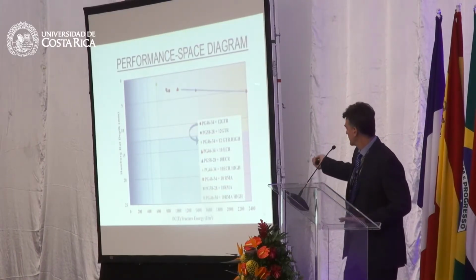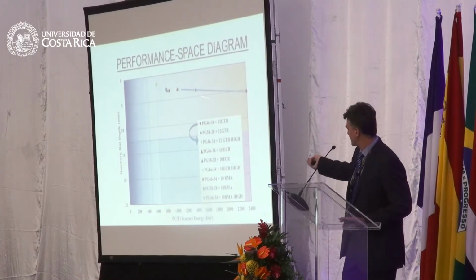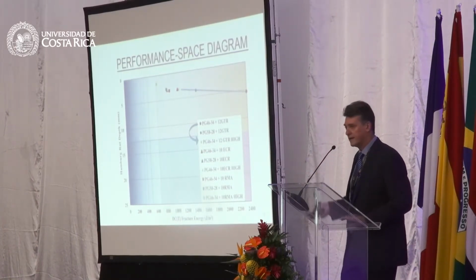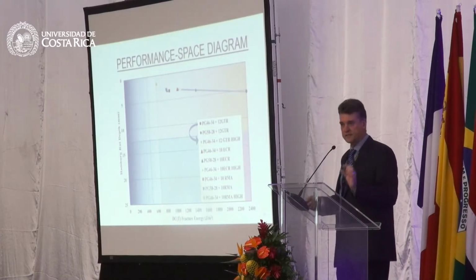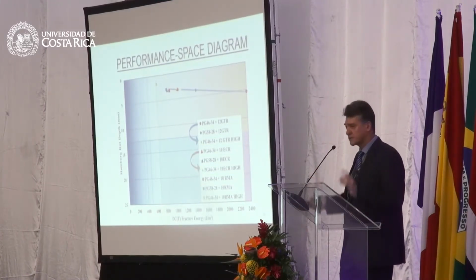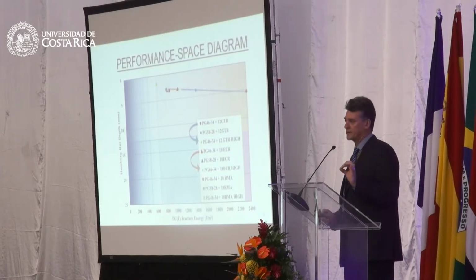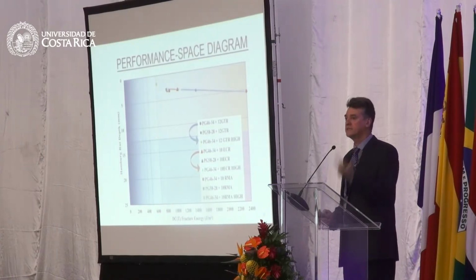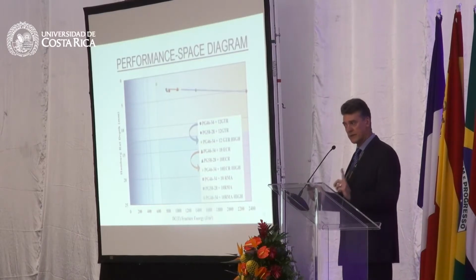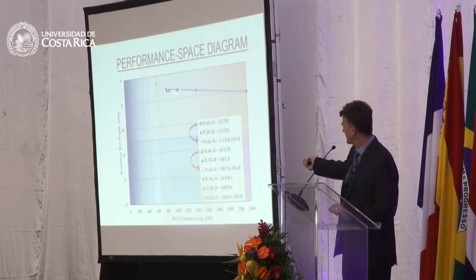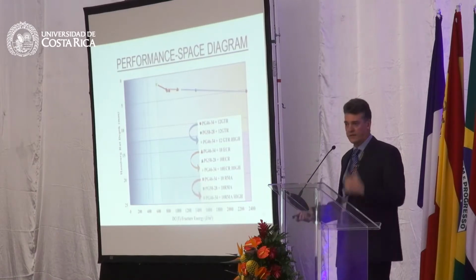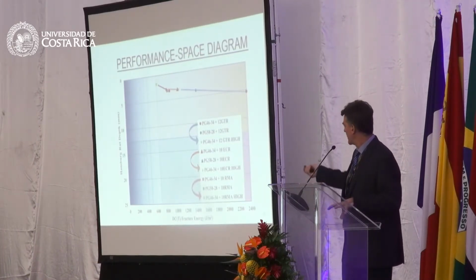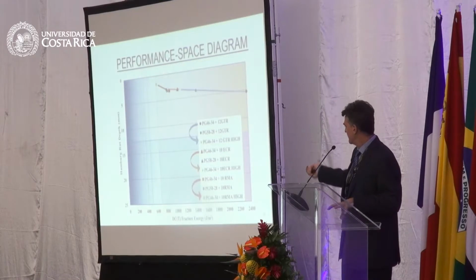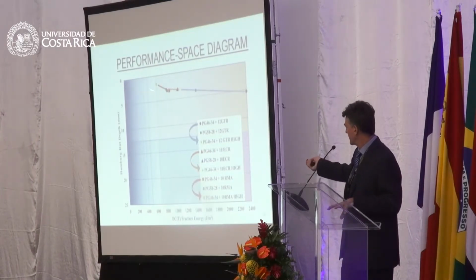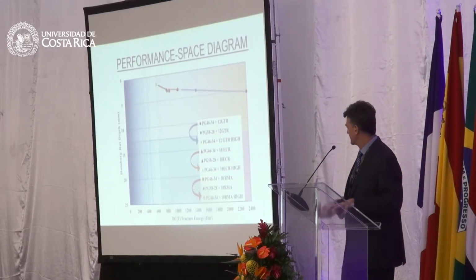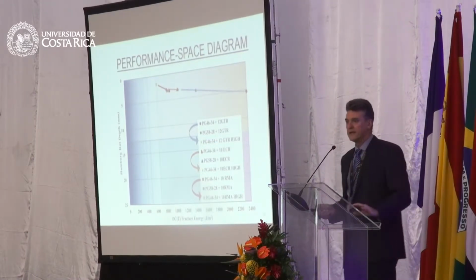The Seneca product had the highest fracture energy. It's furthest out to the right and fell along the line. The dry process, the ECR product, is the least expensive product, and contractors feel like it's the easiest one to use. So contractors like this new dry process. It fell in the middle, and then the other new terminal blend process, the RMA product, fell on the stiffer side with the lowest rutting and the lowest fracture resistance. But they did follow this trend.